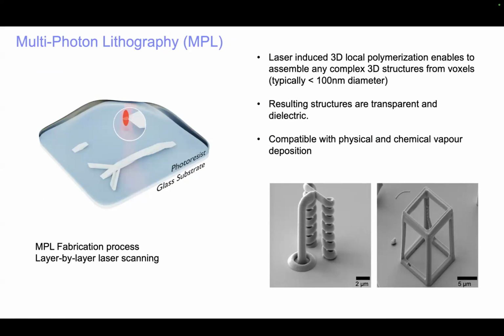And here another one of my students, Andre Farina, built a technique. In principle, we should show it, but it's not showing. We basically have a super resolution optical laser beam with a very high intensity, and that is used to cause polymerization of a complex polymer mixture, which includes some kind of photosensitive component. And in this way, we can build three-dimensional structures. It's a super resolution microscope, and we can build structures from polymers with a pixel size of 50 nanometers, which is several times better than any commercially available 3D printing system. So on the right-hand side, you can see some structures that Andre built just to demonstrate the possibilities.